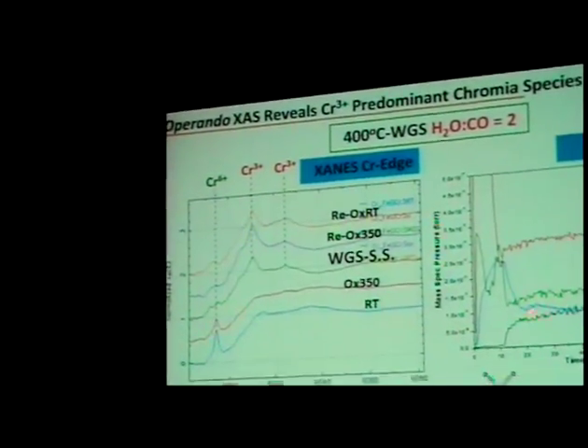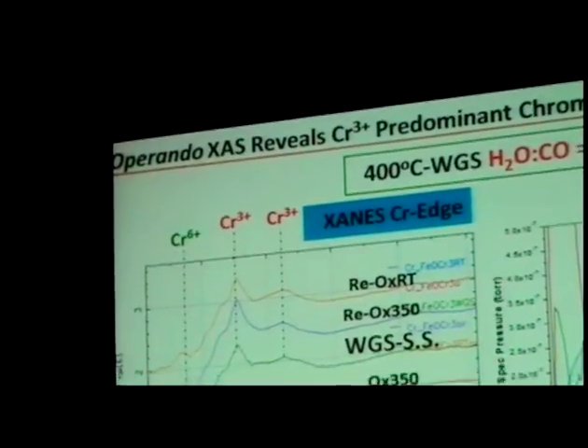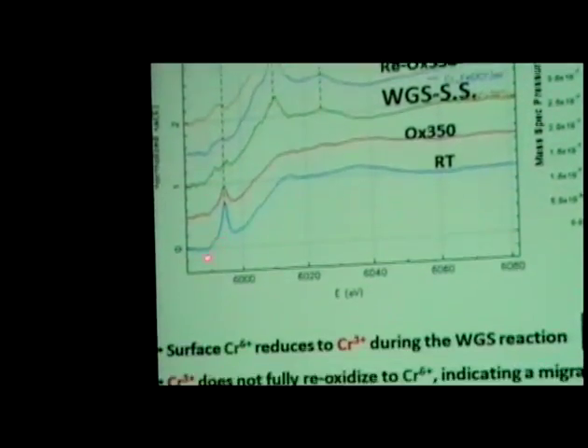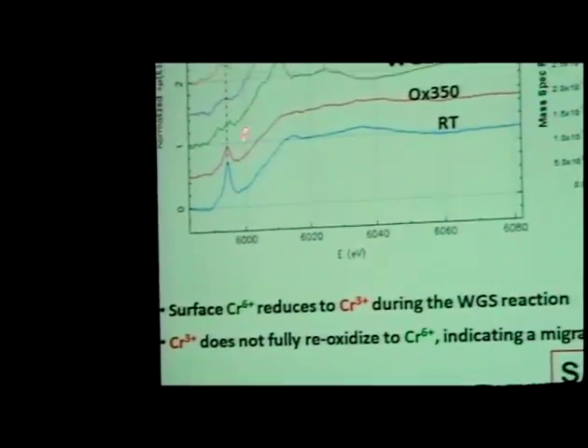To learn more about what's going on with the chromium, we turn to in situ XANES. So again, here is the XANES information. Here's the mass spec confirming that we're doing water gas shift. So we start off, you get this nice pre-edge. This pre-edge here is chromium 6.